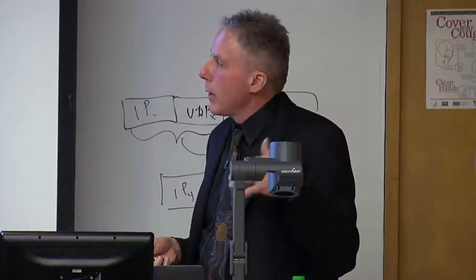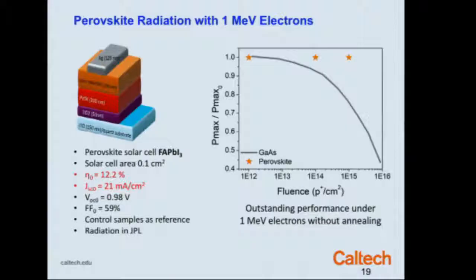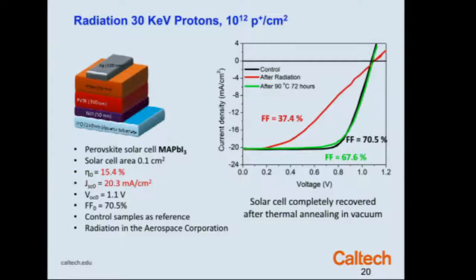So that implies that I could potentially, at least in terms of the electron performance, operate this with no radiation shield. Here is with proton irradiation. And this story's a little, the plot thickens a little bit. Same kind of cell here. It's an absorber layer. We have electron and hole transport layers here, nickel oxide for hole and PCBM for electrons. And then we have a transparent substrate here that this has been made on. So upon proton irradiation, we find that the solar cell voltage stays exactly the same. The short circuit current density stays exactly the same, but the fill factor changes.